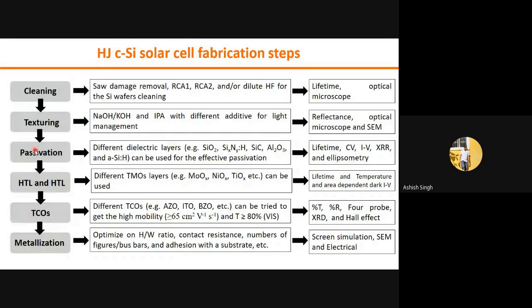Then finally, passivation can be tried with different dielectric materials like silicon oxide, silicon nitride, Al2O3, and so on. The characterization should be lifetime, CV (capacitance voltage) measurement, IV measurement, XRR, and ellipsometry. Then after that we can make the hole transport layer and electron transport layer with different transition metal oxide layers, and the characterization will be the lifetime and temperature and area dependent dark IV. Then finally, we need to deposit the transparent conductor and metallization.